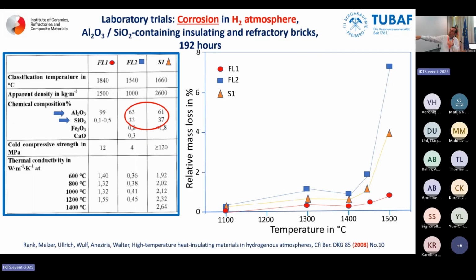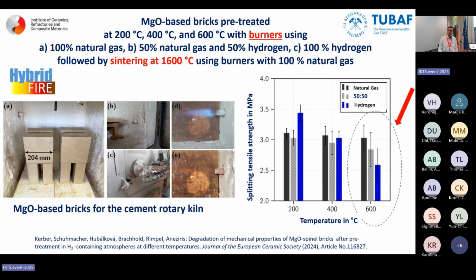And we have seen here in 2008 the impact that if we have not used pure aluminas, but also alumina silicate systems, above 1400 degrees, everything goes in the air. What we have done is we have made a pre-treatment of original MgO-based bricks for the cement rotary kiln, and we have used 200, 400, 600 degrees temperature in a pre-treatment, natural gas 100%, 100% hydrogen, the blue ones, and a 50-50. And then we have fired them in the Refratechnik kiln that you saw before at 1600 degrees Celsius.